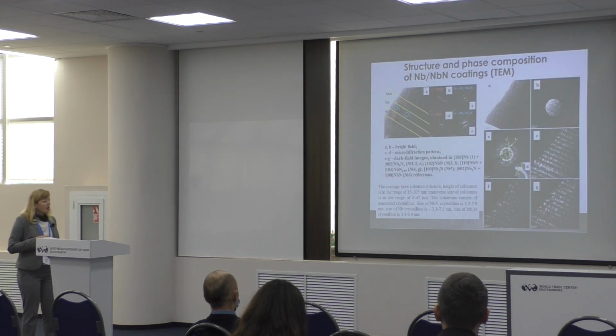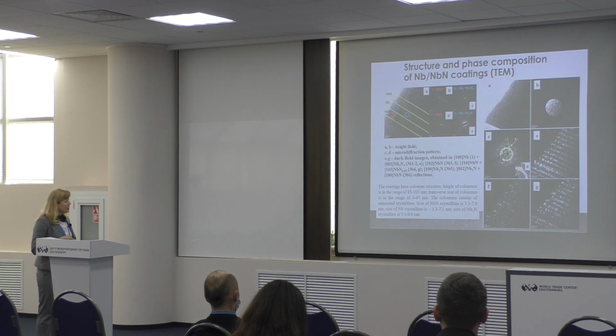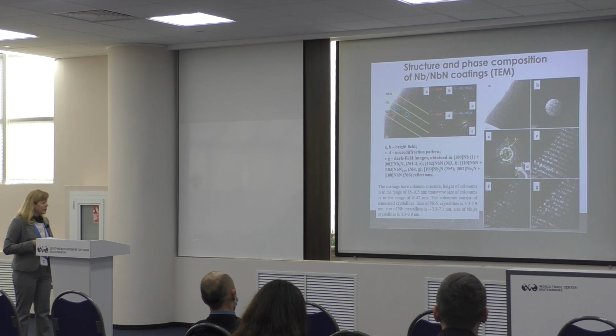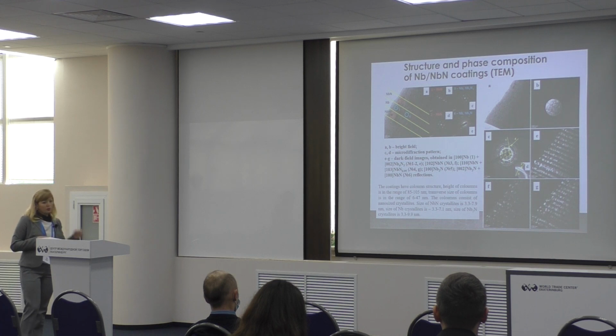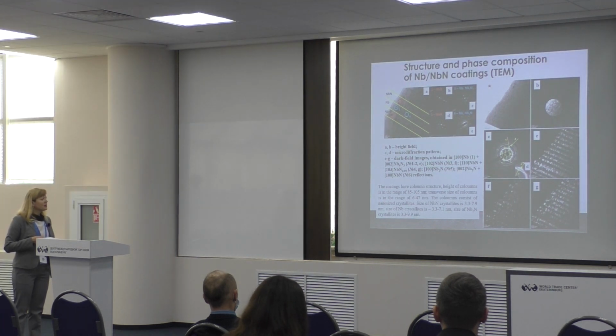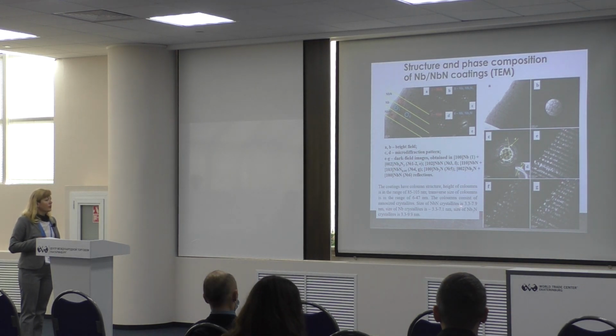Detailed research by transmission electron microscope showed that the metal layer consists of niobium and niobium 2 nitride, niobium 4 nitride 3 phase, and the nitride layers consist of niobium nitride phase. The coatings have a column structure. Height of column is in the range of 85 to 105 nanometers. Transverse size of columns is in the range of 6 to 47 nanometers. The column consists of nano-sized crystallites from 3 to 10 nanometers.